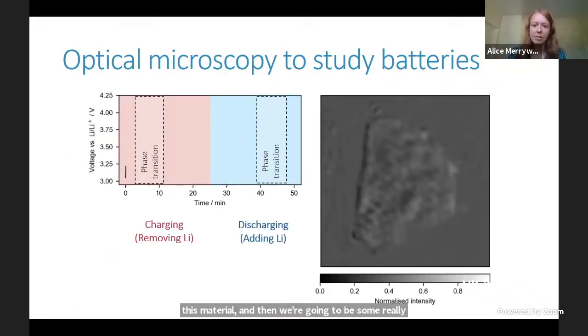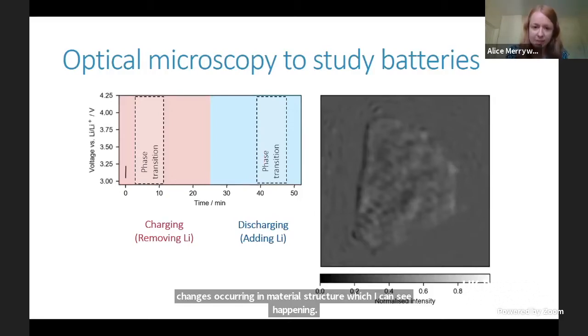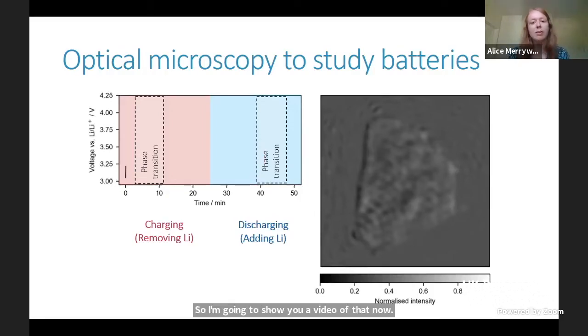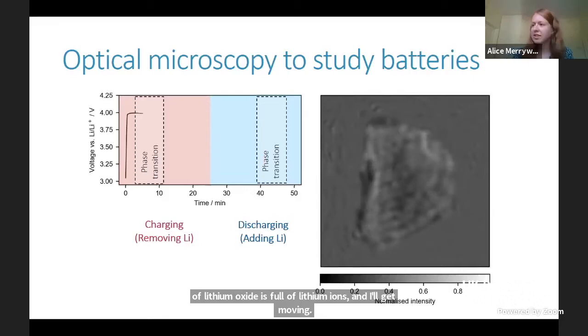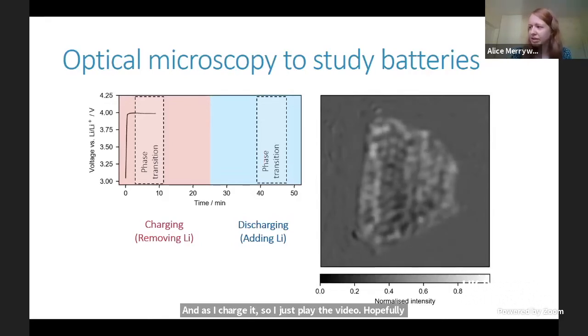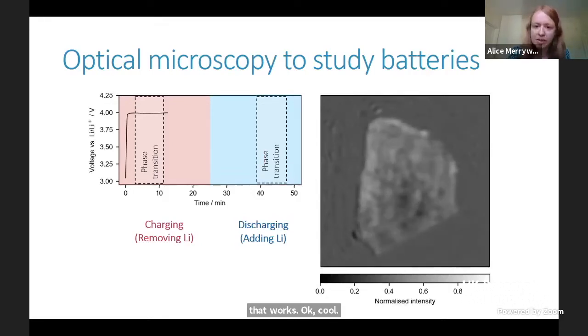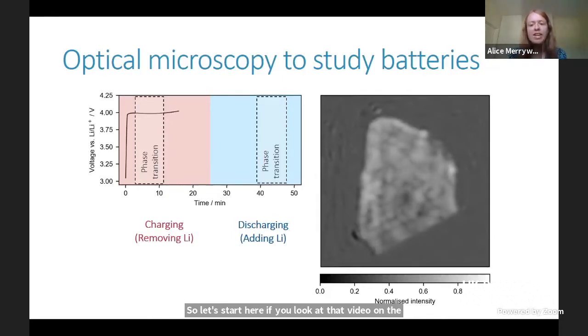So this is going to be a video where I charge and then I discharge my battery. And to start with, our particle of lithium cobalt oxide is full of lithium ions, and I'm going to be removing them as I charge it. So I'll just play the video and hopefully that works. Okay, cool. So near the start here, if you look at that video on the right, you can see some things starting to move across the particle. And that's a new phase developing in the material, which contains a lower amount of lithium moving across it.